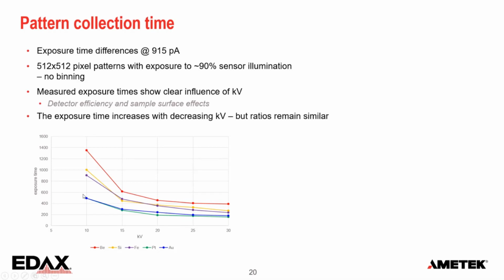And what happens there is a combination of the backscatter coefficient. We saw that before, but its main effect is the sample surface. The lower the kV, the more sensitive your signal is going to get to any contamination or any surface defects from the preparation or oxidation, perhaps. And on top, there's also a certain detector efficiency, because with lower kV, you're getting fewer electron-hole pairs in the sensor, so you have a little bit less detection.